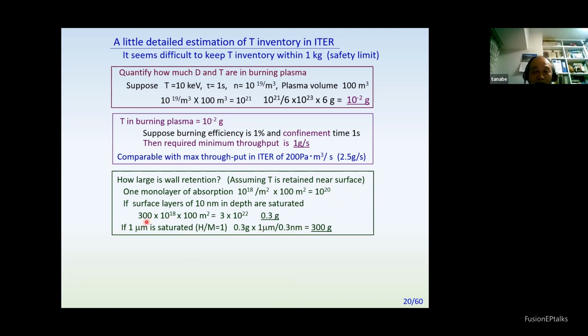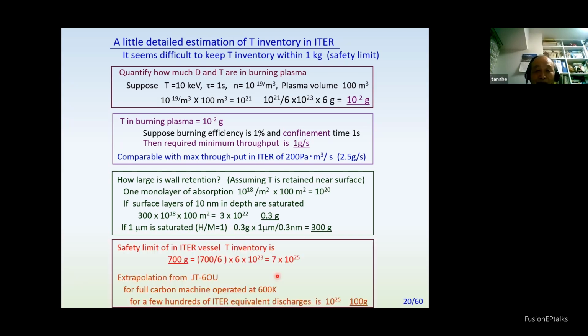And if 1 micrometer from the surface is saturated by tritium, with a metal atom to H ratio of 1, then this comes to 300 grams. Compared to the safety limit of ITER vessels, 700 grams - this is rather the main reason this number is coming up.